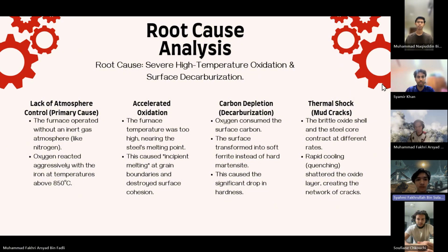The root cause for the material is severe high temperature oxidation and surface decarburization. So this failure mechanism occurs in the following sequence. First, is lack of atmosphere control. This is the primary cause. The furnace operated without an inert gas atmosphere like nitrogen. So oxygen reacts aggressively with the iron at temperatures above 850 degrees Celsius, which causes the oxidation.